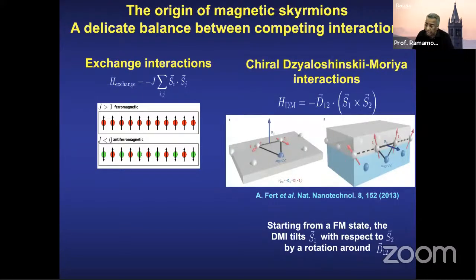Now, in reality, when you write down the full free energy functional, you also have to include the cross product, S1 cross S2. In many systems, in 95% of the systems, that cross product term will drop out because of the symmetry of the crystal, like iron, for example, which has too high a symmetry, body-centered cubic. On the other hand, if you have an interface, it automatically breaks inversion symmetry. And therefore, you could have at the interface a very strong S1 cross S2. It shows up with this vector called the Dzyaloshinskii-Moriya vector. Igor Dzyaloshinskii back in the late 50s and Professor Moriya at Bell Labs discovered this so-called antisymmetric coupling. An interface can create that. Spin-orbit coupling is a very important component of that. Professor Pert, who's a dear friend of mine, has a beautiful review article. You should read it.